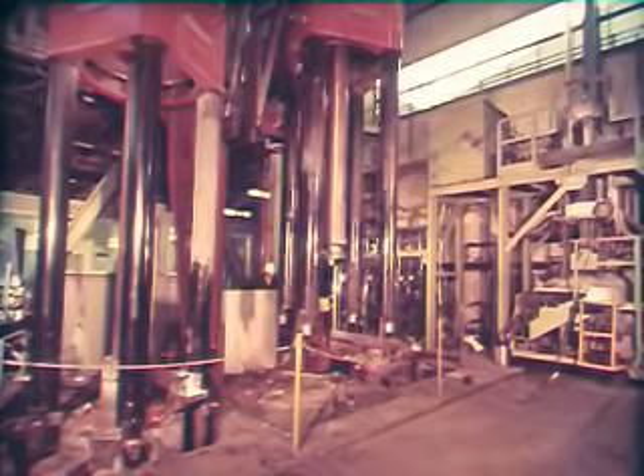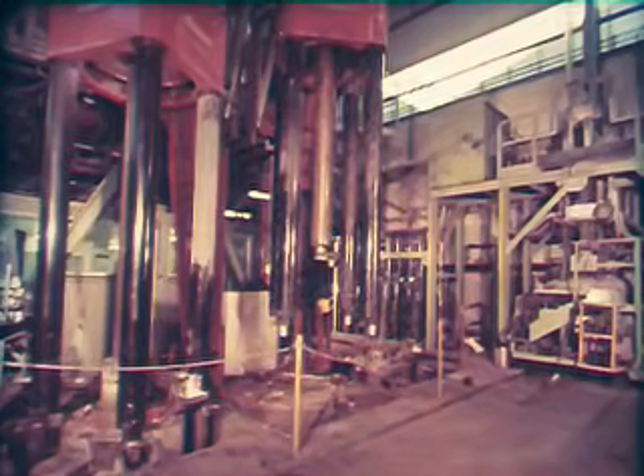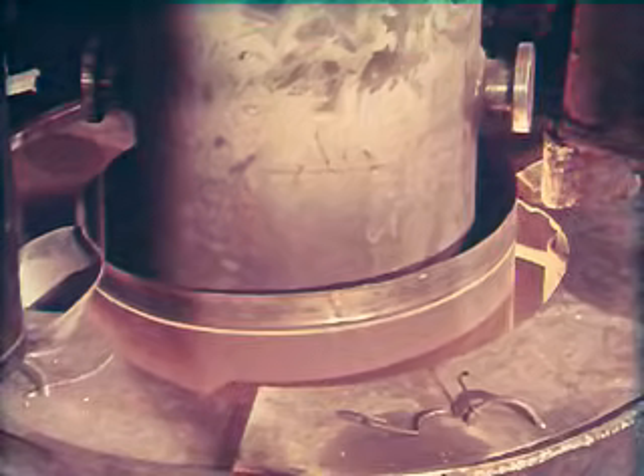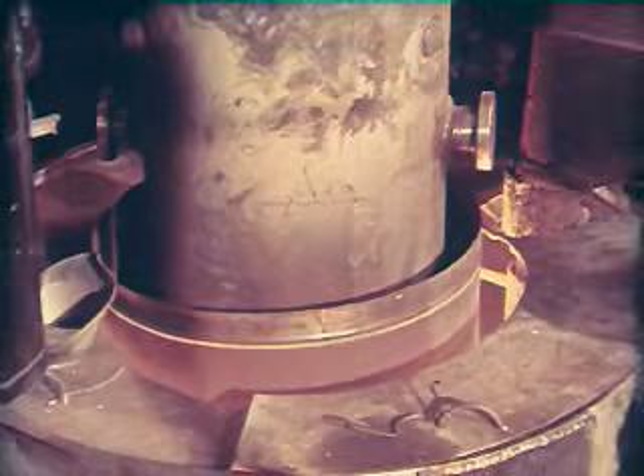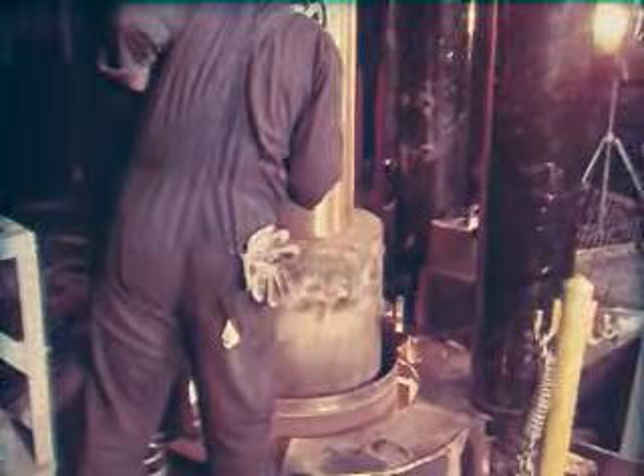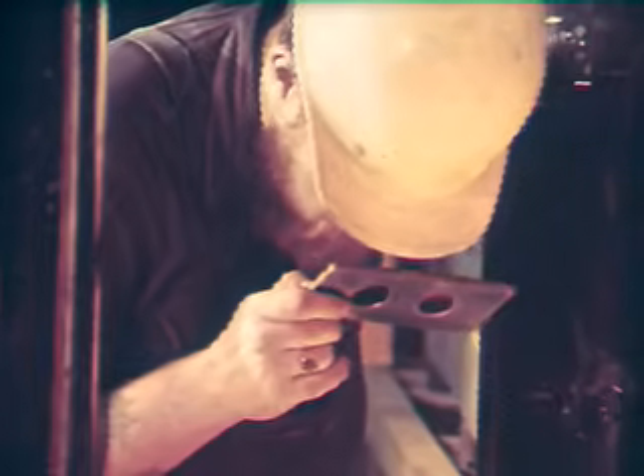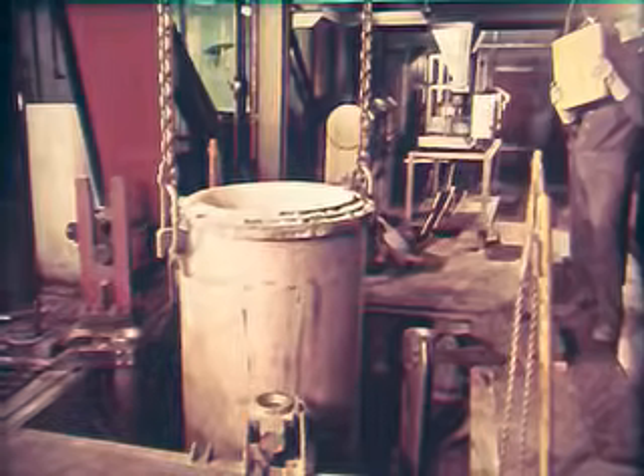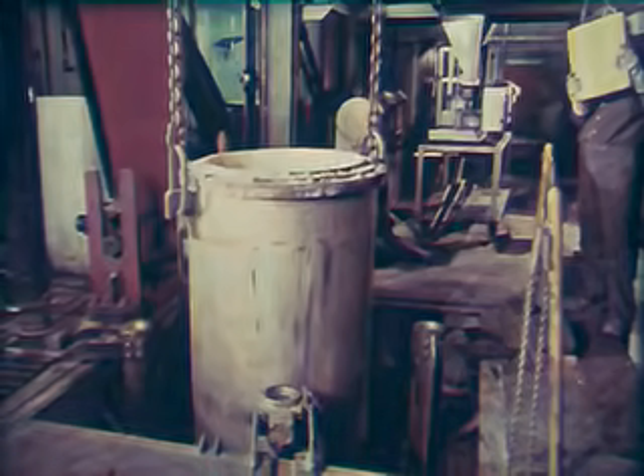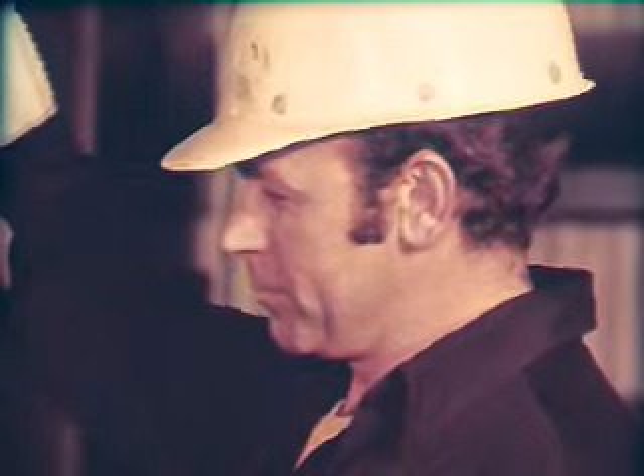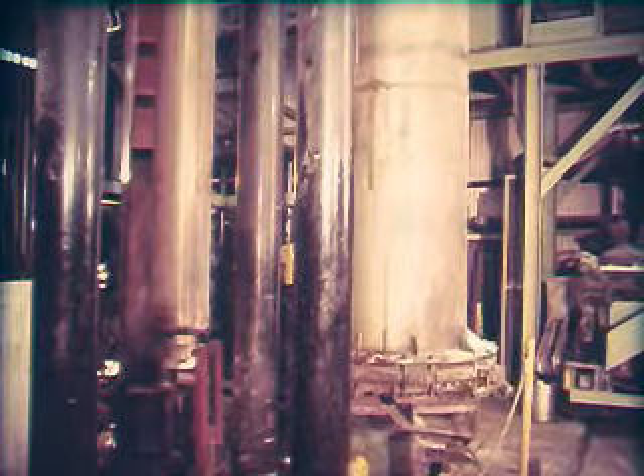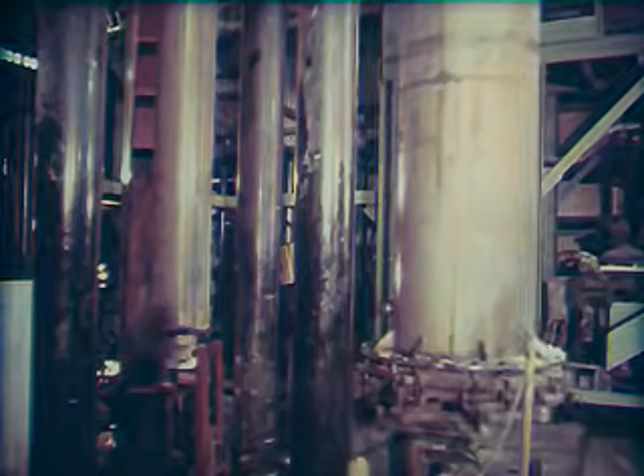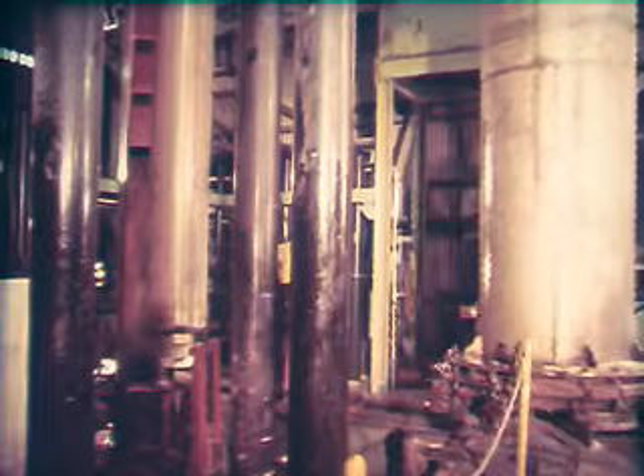Some special steels are refined even further in this electroslag refining unit. The electroslag refining process and the subsequent controlled solidification result in a high purity and homogeneous product with a greatly improved service performance. ESR product is characterised by a significant increase in fatigue properties, transverse ductility and fracture toughness.